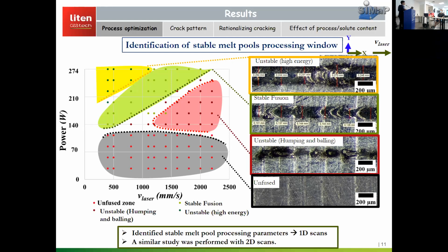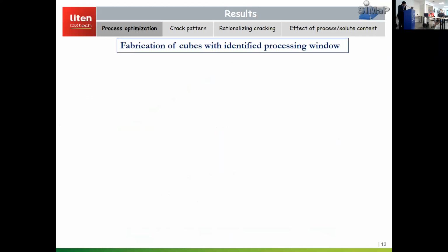Now, a similar processing map was identified for the 2D conditions. The 2D condition basically was to understand the effect of a laser passing just adjacent to the previous laser track. So similar conclusions were found using the 2D analysis. So now, we have identified stable melting conditions. Let's see what its effect is when we finally 3D print the cubes. For finally 3D printing the cubes, we chose a simple scanning strategy without any rotation between the two layers. The choice of this strategy was basically to have a simple microstructure which is easy to interpret.